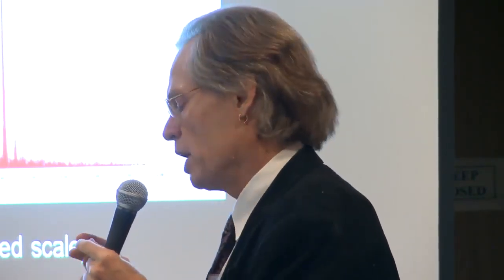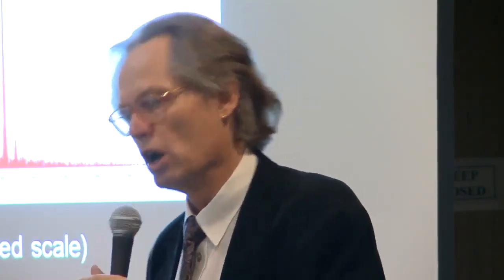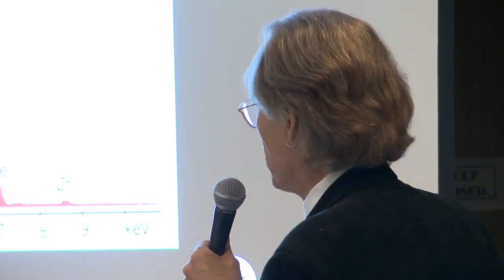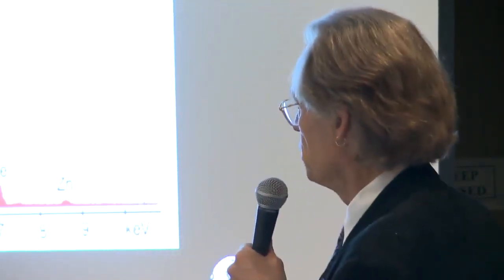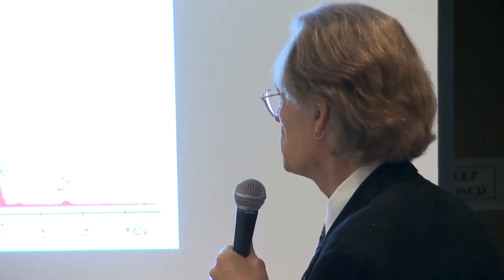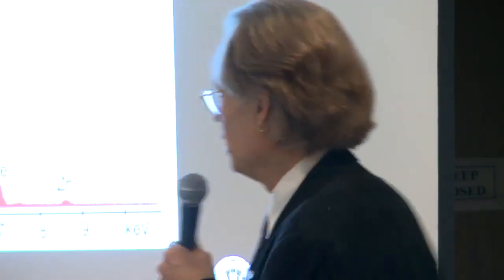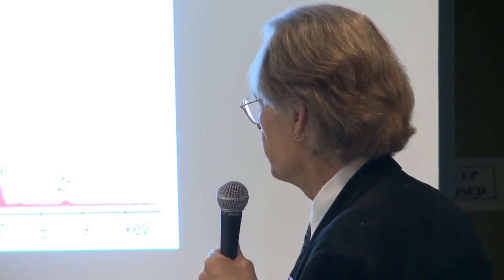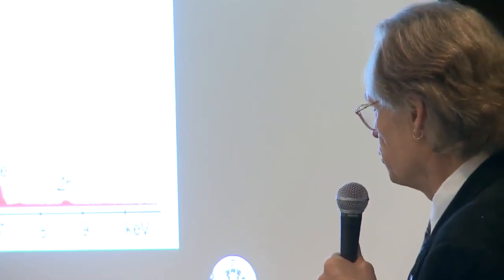Now, in the experiment where we had to put the chip into methyl ethyl ketone, we could not break it, of course. So this actually shows all the contamination from the rest of the building. Let me just point out here, you see a great big sulfur peak, and you see calcium is big. We've already talked about wallboard. This is contamination of calcium sulfate from the wallboard, which was all over. And this zinc chromate could very well be primer paint sticking on the outside of the red-gray chips. And the point is, when you break the chip, where you get a clean cut, there is no zinc chromate. That is one reason that the red-gray chips are not the primer paint.